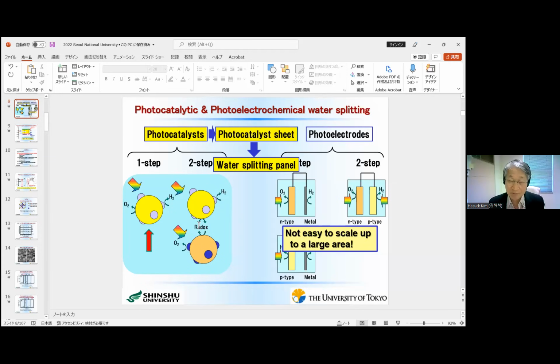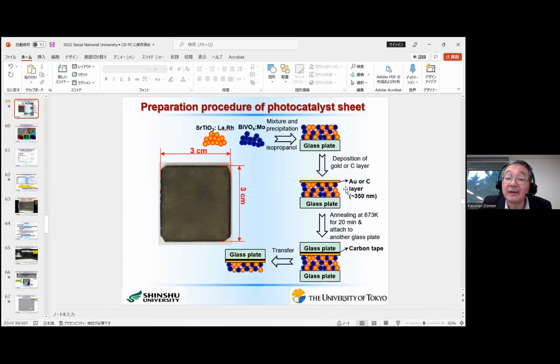some kind of probability would be lower for those two catalysts to collide with each other. They use some redox shuttles, iron 2+, 3+. But if we use our photocatalyst sheet, we can use this kind of electron and hole conducting layer here. So this seems to work better than the redox shuttle in the suspended system. That's why we can get much better activity.